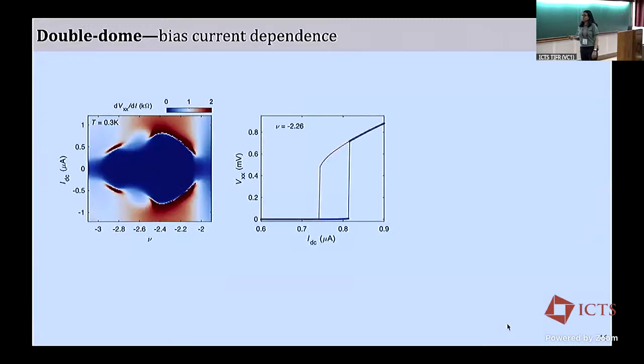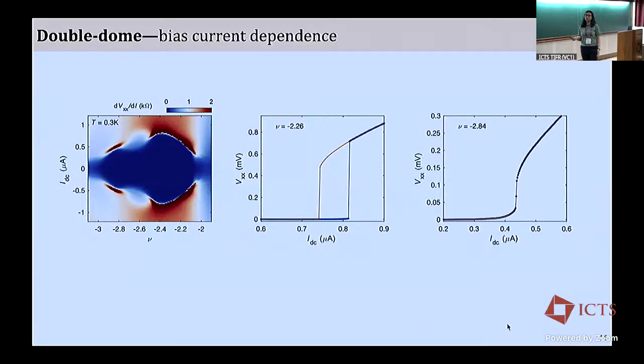So the other thing that we could do is the bias current dependence. And if you look at the right and left dome, you will see that there is also a striking difference. While the right dome looks like a normal superconductor, where you expect a hysteresis because there can be some heating effect, in the left dome you can think of some quasiparticles that are dissipating the heat, and hence they overlap with each other when we go back and forth.